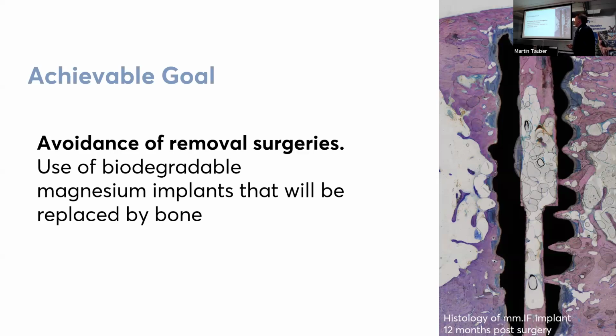That's something you can see at least partially in the histological image that is shown here, where a device is partially degraded. So the black area marks is still the metal, but you can see where there was a thread in this cross section. It's partially gone and sometimes turned into bone cells already, which is the very violet colored sections here. And the bone seems to pretty nicely align to the surface of the implant.